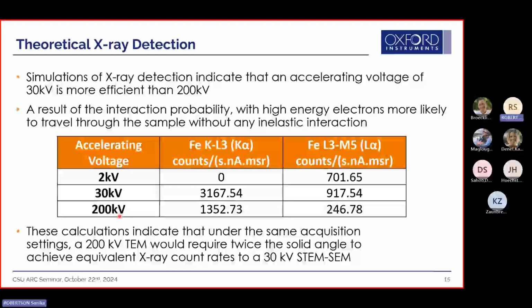So in a TEM, you'll have typical 200 kV, and look at the count rates. You get a certain signal, but the issue is at such high energies, you have a lot of the electrons just passing through, and there's not enough time for them to interact with the material. So the X-ray generation is actually limited.